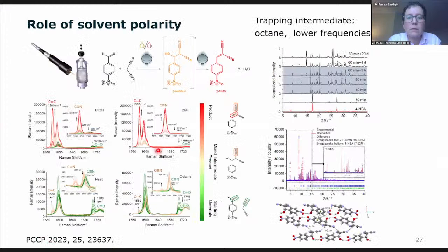Okay. In this case, we have a real chemical reaction we are observing, and here we really have a two-step process. The second step would be the elimination reaction, and we know that nonpolar solvents or neat grinding conditions would not really enhance that step, but the polar solvents would, and therefore it's clear that for ethanol and DMF the reaction is faster. But that has to do with the chemistry we are looking at.